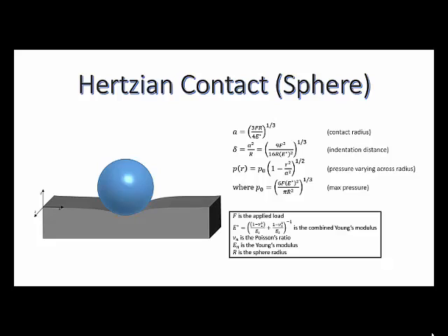We know from our experience and our engineering intuition that both the ball and the surface will deform a certain amount, depending on the amount of force applied. If we ignore the effect of adhesion, you may recognize that this is the phenomenon known as Hertzian contact, which we studied in depth earlier this semester, and found that we could relate variables of load, contact radius, indentation depth, and contact pressure using only the ball's radius and the Young's modulus and Poisson's ratio of the two materials. The derivation of these values is a little involved, but you end up with these equations.